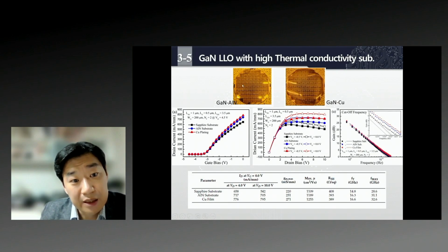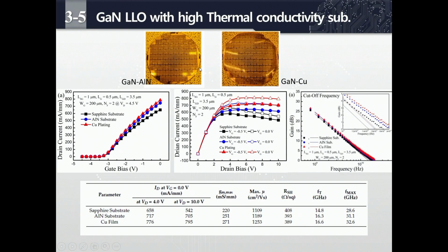Here we can see the GaN aluminum nitride LLO package is quite flat. And the other one is the GaN copper LLO package. It has a high bow because the copper plating is very thick, around 500 micrometers of copper. And this picture shows the transfer characteristics and output characteristics. We can see the GaN sapphire substrate has a strong self-heating effect and lower drain current. The aluminum nitride substrate is better, with around 40% improvement. And the best one is the copper plating. It also shows very constant behavior and suppression of the self-heating effect here.